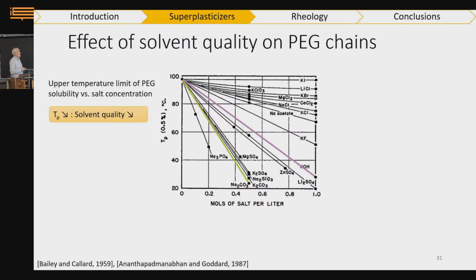So you see that it drops with the concentration in salts. That is the first information. The second very important information is that it depends on the anions. You see the solvent quality is more efficiently degraded by phosphates than by sulfates, carbonates, or hydroxides. And again, if you look in the literature, this year you still have people publishing articles trying to understand why. It relates, obviously, to the Hofmeister series, for those of you that are chemists. It has to do with the radius and the charge of the anions, but this is still debated, okay? This is not very clear. The Hofmeister series is actually an empirical knowledge. This notion of soft and hard ions is not very clear in the literature, and as I said, there are still people publishing theoretical papers trying to explain that.